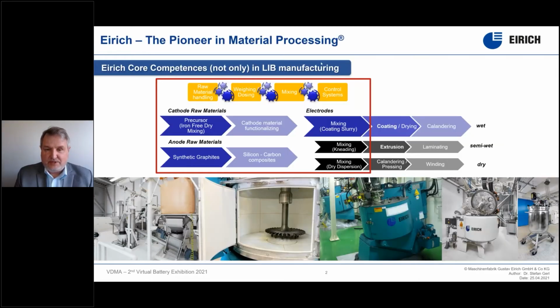Ladies and gentlemen, I would like to start with a short overview of the EIRICH activities in the field of lithium-ion battery manufacturing. We are not only in the area of preparation of coating slurry. EIRICH supplied machines already in the preparation of raw materials like cathode material preparation, where precursors are mixed with the lithium source, or the next step, the so-called functionalization of the cathode material to improve the cathode material properties in the final electrode. The same EIRICH machines are supplied in synthetic graphite preparation, where pitch and coke are mixed homogeneously and kneaded to prepare, with a graphitization process, the anode material. And newer developments like the silicon carbon composites, where also some functionalization has to be done.